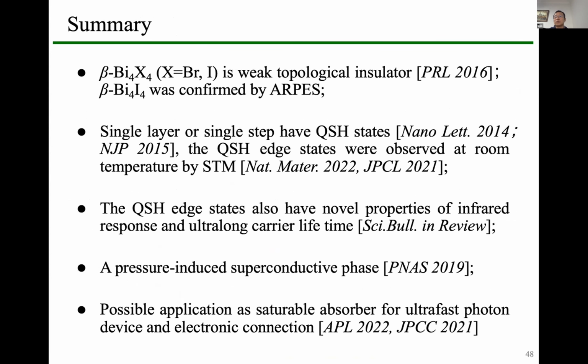So let me give the summary. Basically, we have shown that this kind of beta phase material is a weak topological insulator. This has been confirmed by ARPES experiments. For single layer or single step, they are quantum spin Hall insulator. So we can observe quantum spin Hall states at the single steps, and this can even survive at room temperature. And we can see that these quantum spin Hall edge states have very great properties for infrared response and extremely long carrier lifetime.